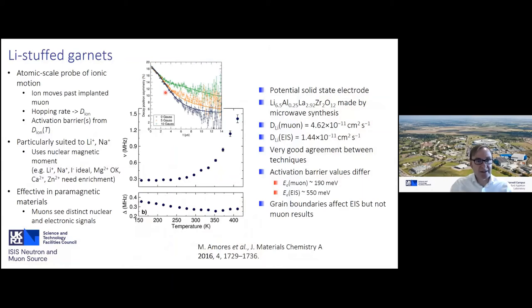Here you can see the muon signal as a function of decay time. Remember, the muon has a lifetime of 2.2 microseconds. So you can infer the hopping rate of the ion from the muon data. If you look at it as a function of temperature, you can work out what the activation barriers are. This doesn't just work for lithium, it works well for sodium, and can work with a whole load of other materials. So next generation battery technologies are probably going to be amenable to this technique.